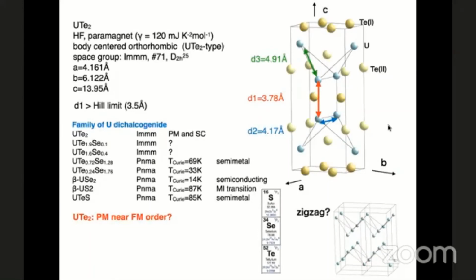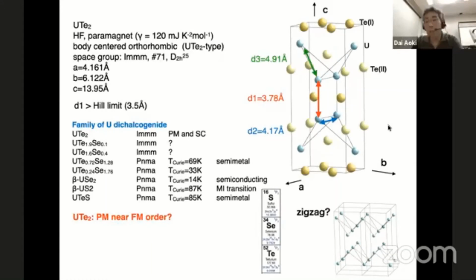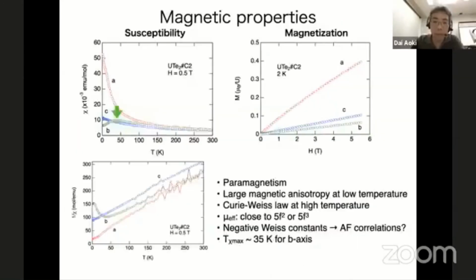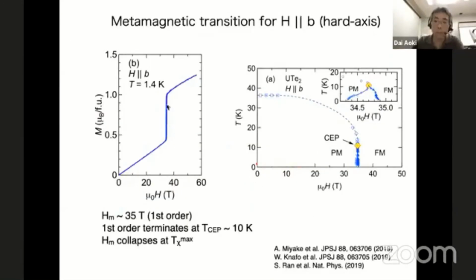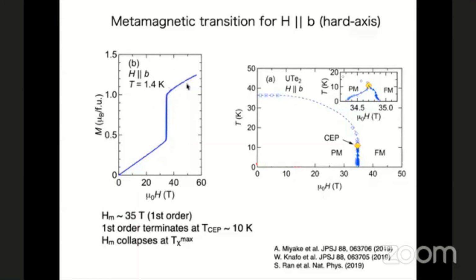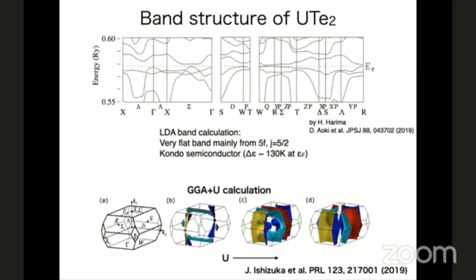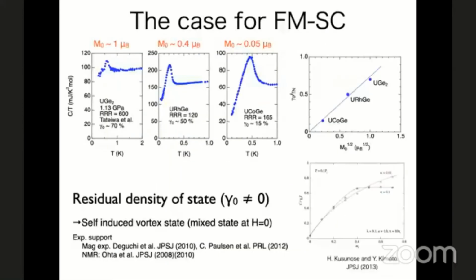Okay, but shouldn't you be able to induce this ferromagnetic order by applying a field along the a-axis? I mean the easy axis. Yeah, I would say it's not the a-axis, but the b-axis, the hard axis. So you can see along the b-axis, this is somehow a polarized phase. In the polarized phase, it's like an ordered state, like a reoriented state, like in uranium rhodium germanium.